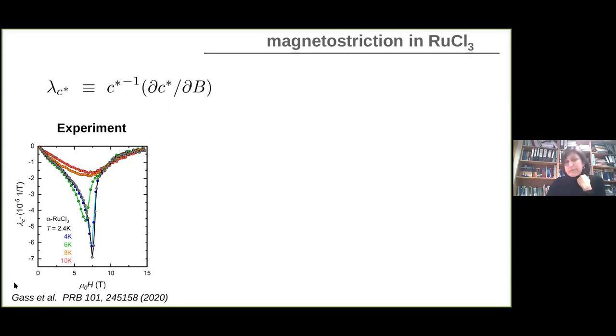So these are in fact experiments from the Dresden group, Gass and collaborators, Anja Wolter and Bernd Büchner, where they measured this magnetostriction as a function of magnetic field. And this is now a magnetic field applied basically parallel to the plane. And what one observes, let me go to very small temperatures, is that this magnetostriction is negative, and it suffers an important change when we reach the magnetic field where the long range order is suppressed in this material. So the lattice is responding very strongly to the magnetic field.